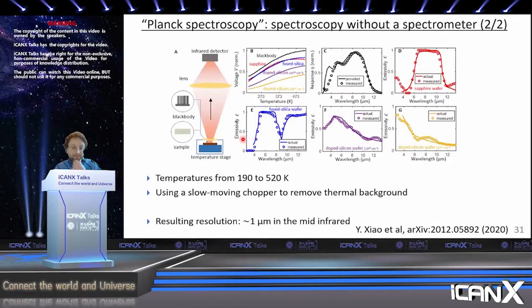So let me show you experimentally how we actually do this. We take this temperature stage and put the sample here. We also put a reference here in this case, and again, it's one of these laboratory black bodies with vertically oriented carbon nanotubes. What we do is measure the voltage that the detector is outputting, so in this case it's just in volts. I'm just normalizing the data over here versus the temperature of your sample. And this is the experimental data that we acquired.